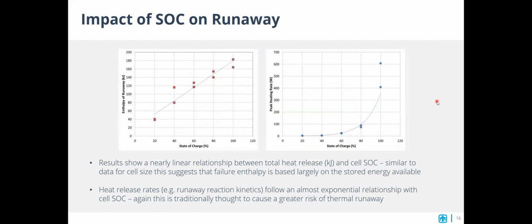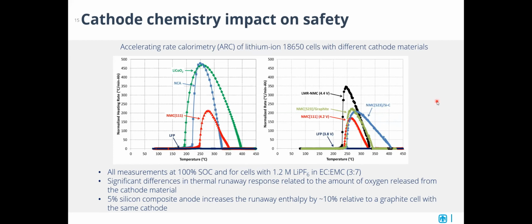There's a question about, can you speak to LFP and its apparent lack of thermal runaway? Yes, so lithium iron phosphate will have a runaway that is not as dramatic as these other chemistries. This phosphate is not an oxide. I believe it doesn't release quite as much oxygen as the other cathode chemistries decomposing. It is also lower voltage, so the total energy stored by an LFP cathode will be less than these other systems.